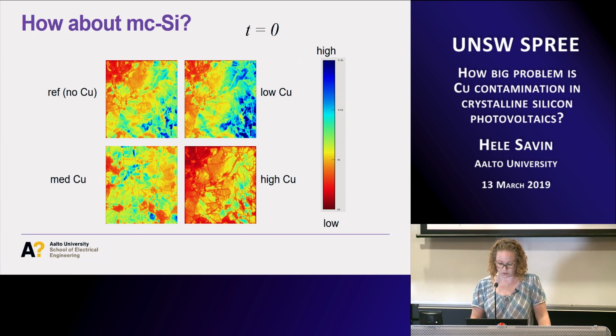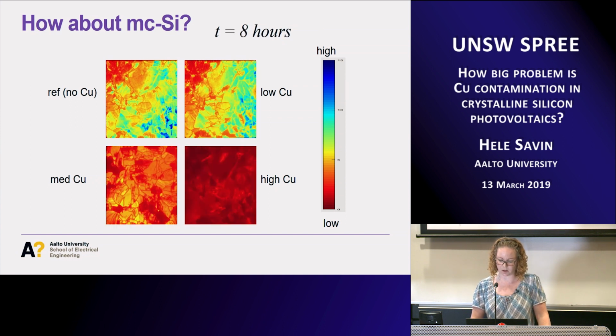But now what happens is when we start illuminating these wafers, we can see 2 minutes, 17 minutes, 3 hours, 8 hours, and we do really see a clear difference also in multicrystalline silicon: the more copper you have, the much higher LID you actually have.